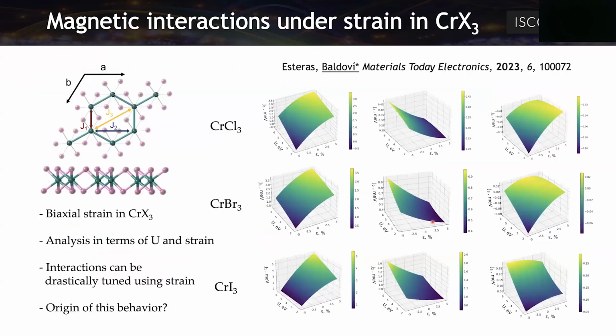We were also testing now the effect of a strain on this magnon gap in the Dirac cones in the magnon dispersion, and testing the effect of exchange interactions and so on. In this case, we can observe that in the case of chromium iodide 3, the exchange interactions are higher. We have the spin orbit coupling in the iodine that is mediated.